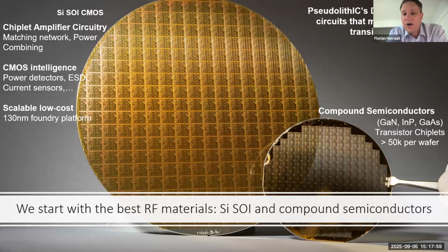And what we do is we only build transistors. So per wafer, one can yield over 50,000 transistor cells. We call these chiplets, right? They're microscopic chips, roughly 200 microns on the side. And what we see is the yield goes really high, because now you repeat the same structure everywhere. So the manufacturing efficiency of each wafer is really high. I'll highlight this in a few minutes with a couple of cartoons to really drive the concept home to you guys.